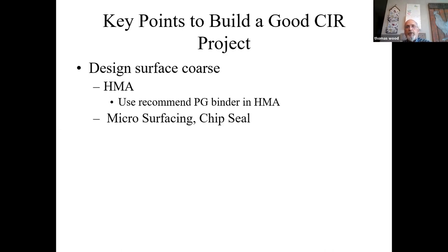And then you can put a chip seal or micro. Like I say, there's one county here in Minnesota that did a project where they microed it and they saved lots of money by micro instead of putting overlay. But there again, they had plenty of structure. I don't remember how thick the pavement was, but after they CIR'd the top four inches, and even with a GE of 1.5 in the existing, they had more than enough strength for the anticipated traffic on the road.